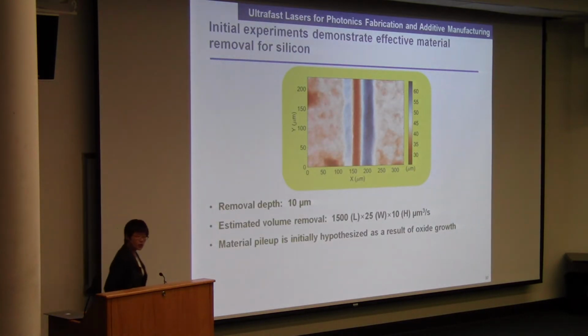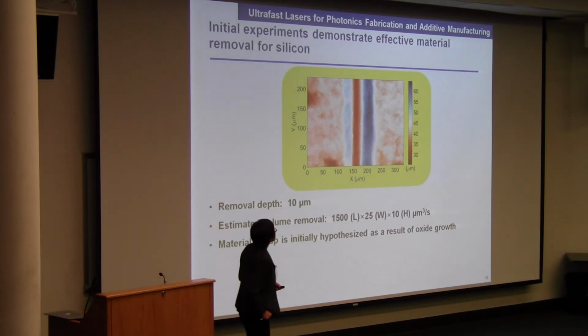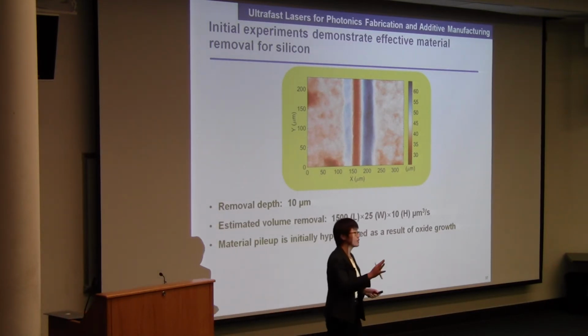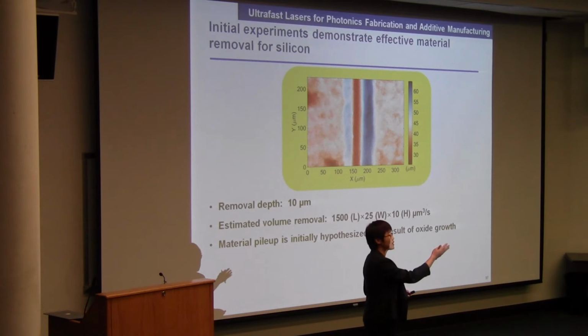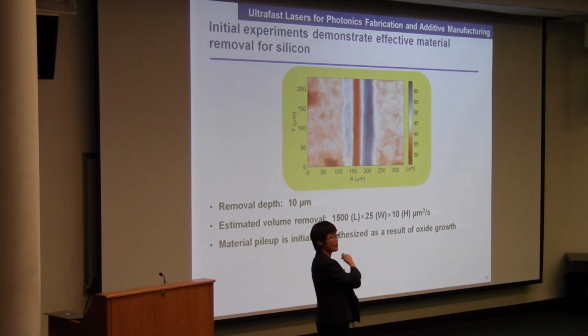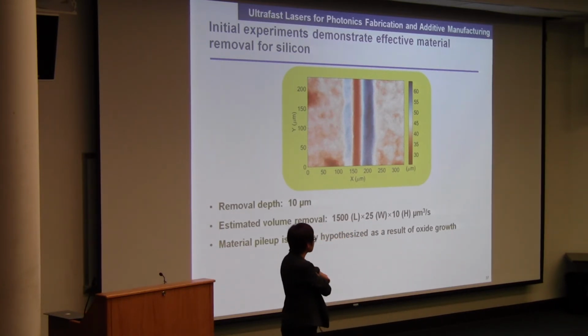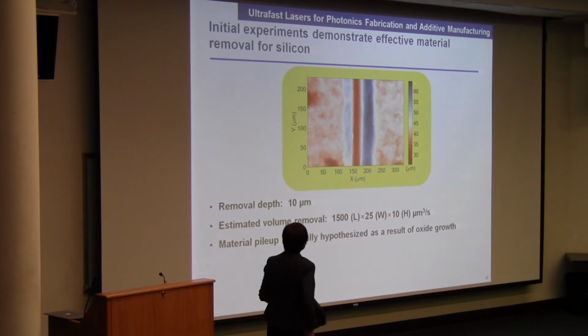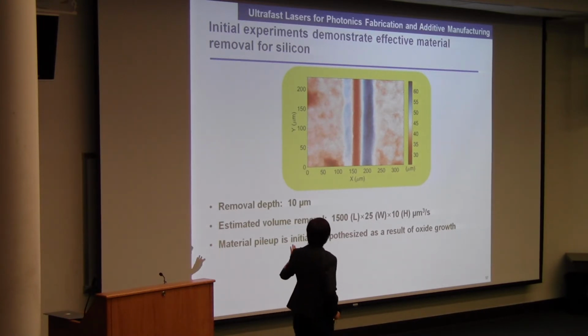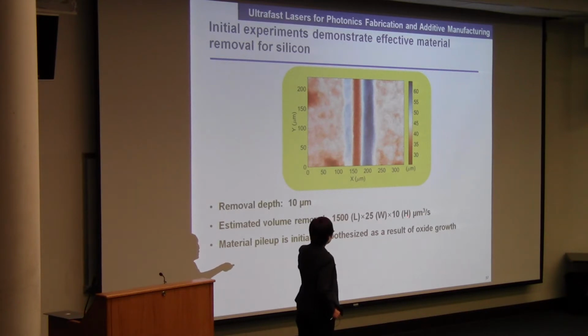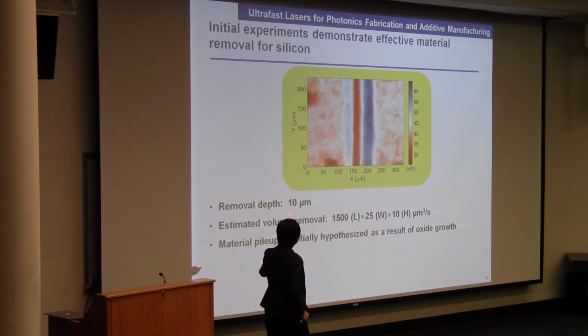The initial experiment demonstrated very effective material removal of silicon. Thanks to Jordan, who gave me that piece of silicon. That's where we were able to demonstrate our silicon result. The estimated volume removal is actually pretty significant, in the cubic micrometer region. The removal depth is about 10 microns.